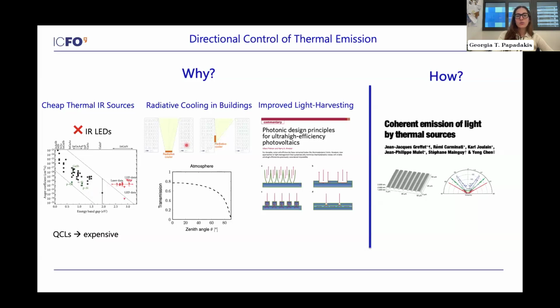Another important reason is that we want to be able to actually control the directionality of radiative cooling, because now that radiative cooling is an actual technology, people don't place coolers just in horizontal structures and on top of buildings, but they actually place them on the side of buildings and in any other configuration that you can think of. And the atmosphere has an angle-dependent transmission coefficient. So taking that into account, you'd really need to get directionality in thermal emission. Another very important reason is that roughly 30% of the losses in the VOC, in the open circuit voltage of solar cells, comes from the fact that the light emitted out of a solar cell is wasted in many directions that are unwanted. So people have been building these very complex configurations for solving this problem. And it boils down to making thermal emission very, very directional.